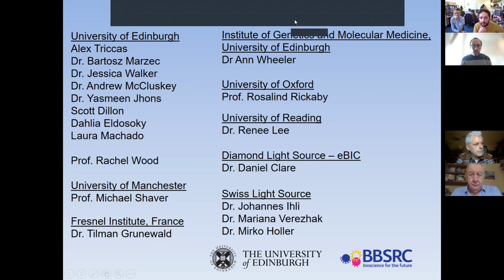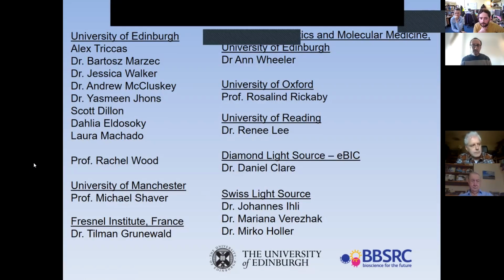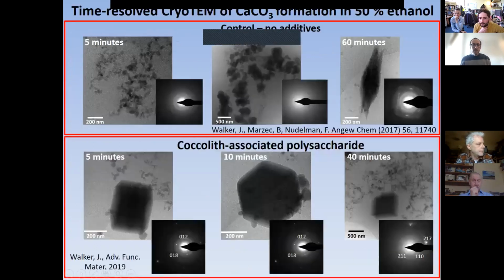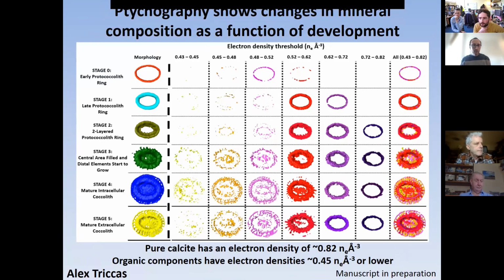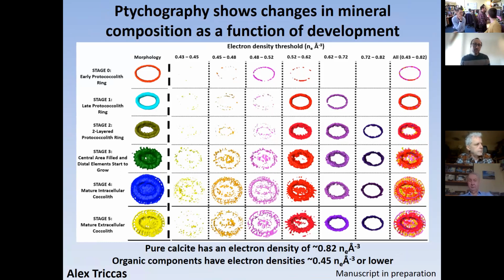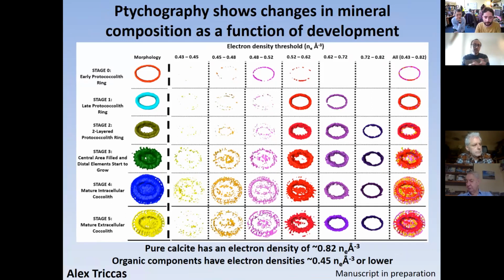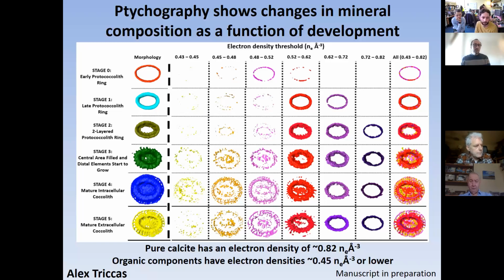Yeah, I think, in terms of computer modeling, I completely agree. I think that is going to be extremely interesting to track. About your second question, you touch on a point that we've been wondering about ourselves. What you mentioned about organic coating causing the decrease in electron density is very much true. This is what we refer to as partial volume effect, which means that we have essentially a voxel, which you can think of as a pixel in 3D. You have both mineral and organic in there. And of course, the resolution of the technique puts them both in the same box, and you end up with a lower electron density. I think that this is very much what is happening when we look at the proximal and distal elements in the coccolith, which are these struts, because they are predominantly very low in electron density.